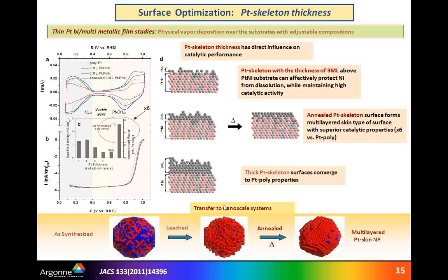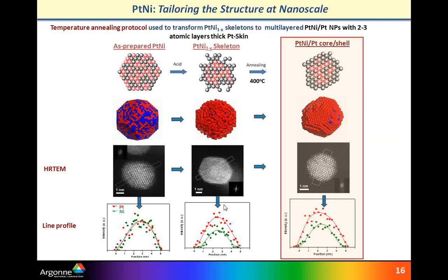So from that point, we took and transferred that knowledge to nanoscale systems, and basically we applied the same protocol. So we used as-prepared platinum nickel particles, then we exposed them to electrochemical environment in order to get platinum skeleton and to get rid of unstable surface nickel, and then we annealed. So the final result was a particle that has up to 2 layers of platinum. And those 2 layers turned out to be extremely beneficial.